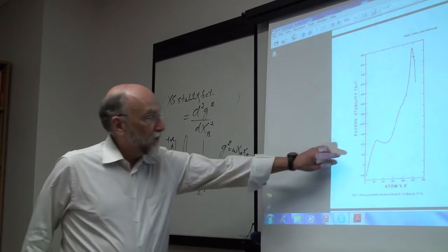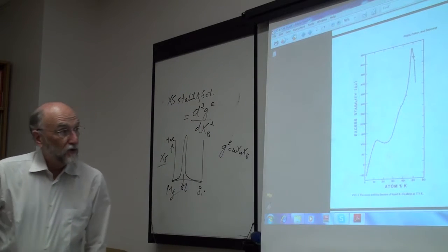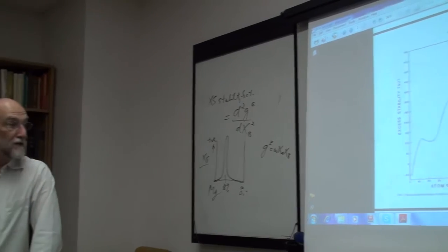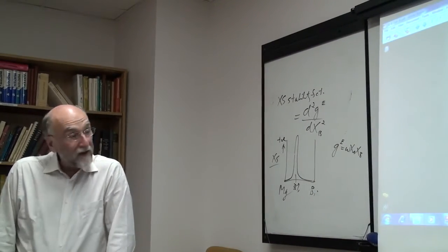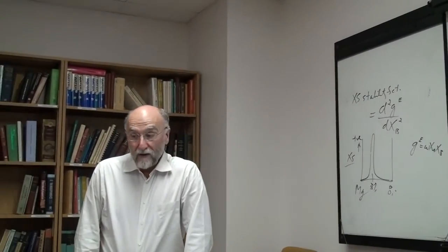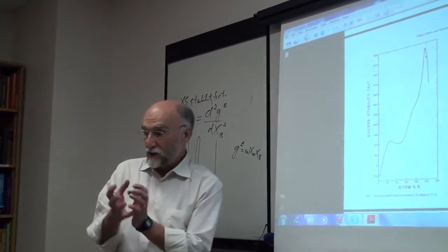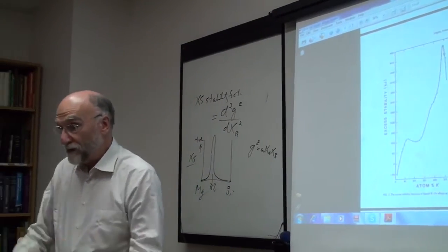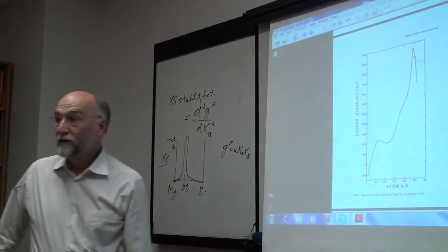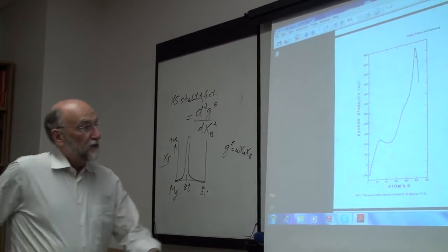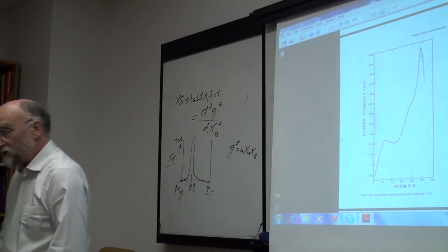But you also have a quite strong peak at about 12.5%, indicating some sort of short-range ordering with about 8 times as many potassiums around a tellurium. I'm not quite sure what that would be, but it's some type of an ordering. You can imagine that locally it almost looks like a solid crystal structure for a few atoms around a central atom. And you may even have another tendency here around 33%. So this indicates as you move across the liquid, it's like moving across a series of intermetallic phases.